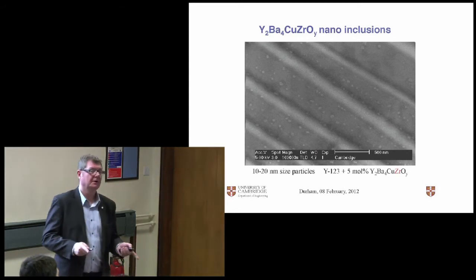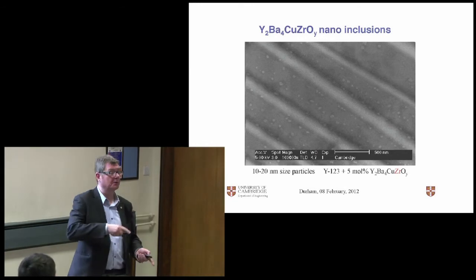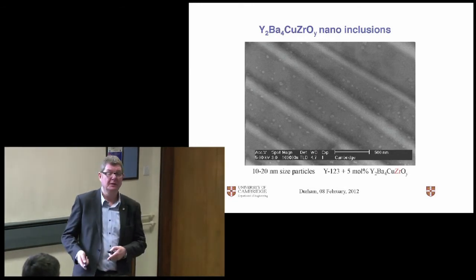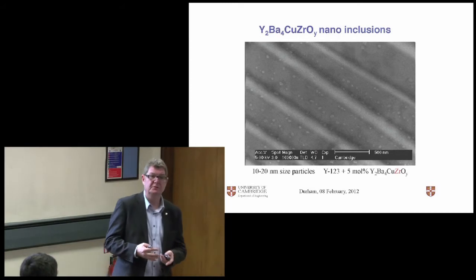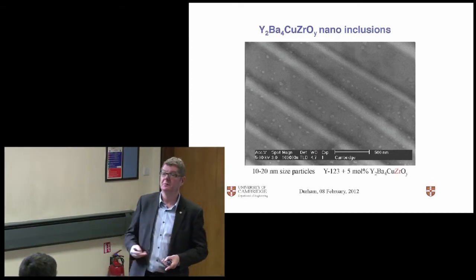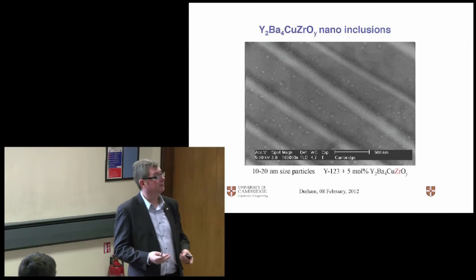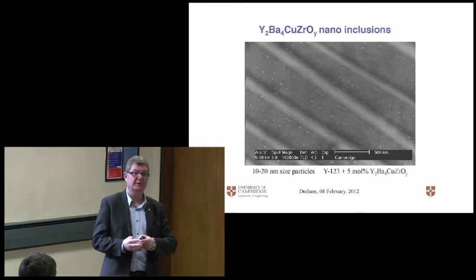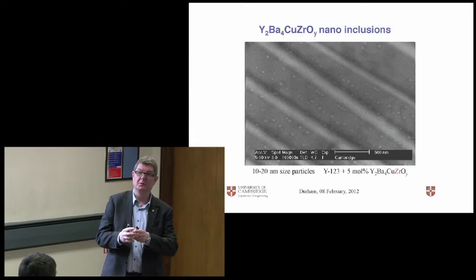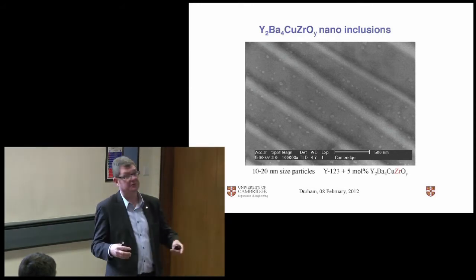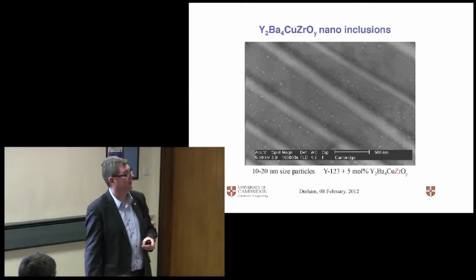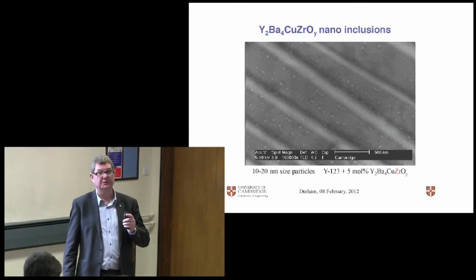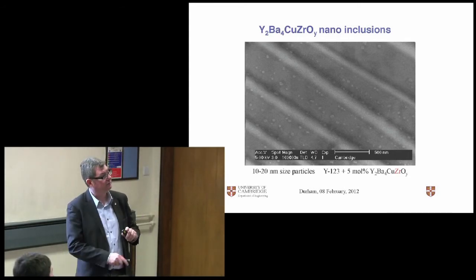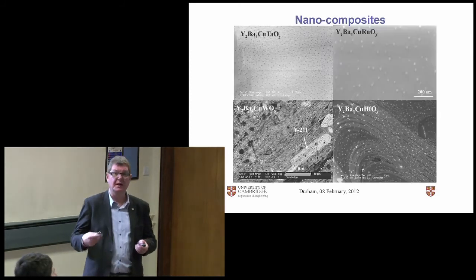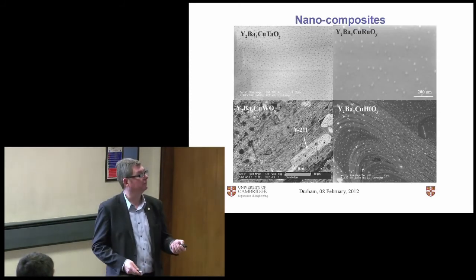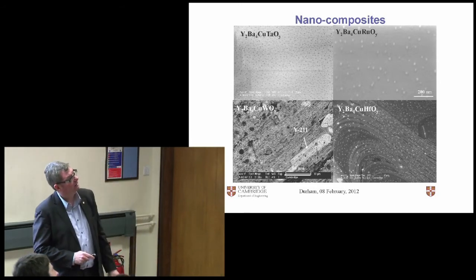And the other thing is that you're not using 211 to control the process and control the pinning. If you want fine 211, it means that you don't have high temperatures for a long time, which means you're limited in your processing. If you want to liberate your processing, you have high temperature for a long time, but 211 materials tend to coarsen. So that means you don't get the pinning. So we made the mistake for more than a decade of trying to do too much with one effect. And as soon as you put in this fine second phase material, that liberates you from worrying about the 211 for pinning. So here's a bunch of others.